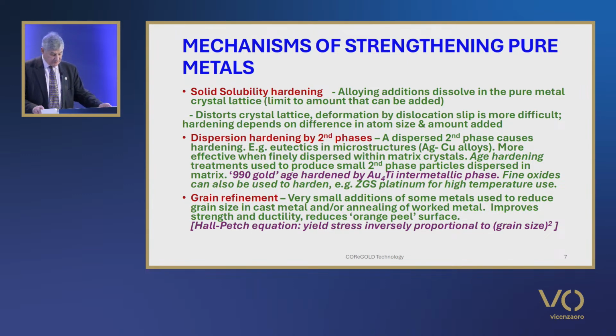Typically, in such alloys, the amount of alloying addition exceeds the limit of solid solubility, and second phases of different composition and/or crystal lattice are formed. By careful processing, these can be precipitated out into the parent metal crystal lattice as dispersions of very fine particles. This is known as age hardening or precipitation hardening, and is commonly utilised in the carat golds and some platinum alloys. The 990 gold-titanium alloy, which I referred to earlier, is hardened by a gold-4-titanium intermetallic phase, for example.